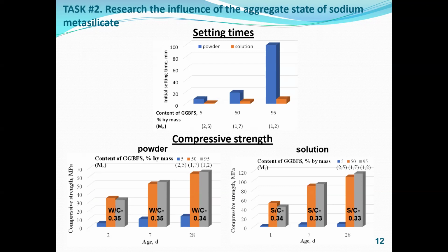of the cement system containing 95% of slag at the age of 1, 7, and 28 days: 43, 51 MPa, 88, 92 MPa, and 108, 115 MPa respectively. The obtained results testify to a necessity to decelerate the rate of structure formation in the alkali-activated cement systems for the whole range of contents of the slag constituents made with sodium metasilicate solution to provide acceptable setting times.